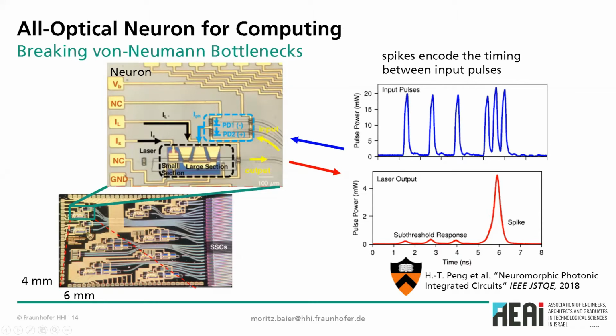Actually, at the beginning, when we received this design, I thought they made an error, but they reassured me that no, this is exactly what they want to do. I just would not really understand why. And well, the reason then later on became clear when they published this paper. So the idea behind this chip design is you launch, say, one optical pulse onto your photodetector. It emits an electrical pulse, which goes into the laser. Now, you bias the laser below threshold, and you bias it such that one of those electrical pulses coming onto the laser is not enough to kick it above threshold. And so you see here sub-threshold responses coming out of the laser. It does not really start lasering if you flick it with one of those pulses.